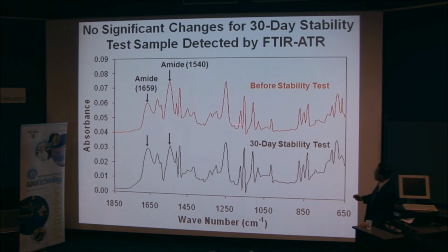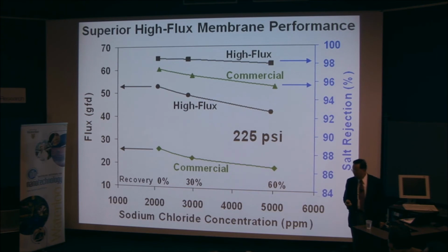When we did the FTIR for the membrane before the test, and also after the 30-day test, it's pretty much identical. So we did not see much of a change, according to the FTIR.